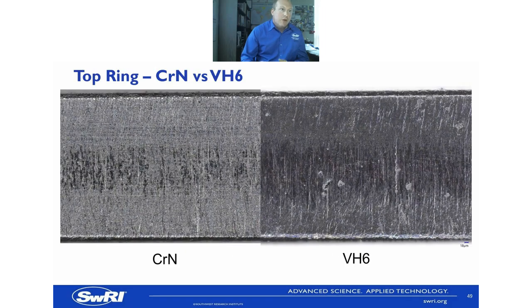Here's a combination of the CRN and the VH6 rings at the end of the test. So you can see that they're working very similarly. You can see that the CRN is quite hard because there's hardly any wear. And you can see on the right-hand side with the VH6 ring, that center line of the top ring where it's been rubbing on the liner, and you can see that's slightly more wear because it's worn off that soft layer and got down to the harder layer.